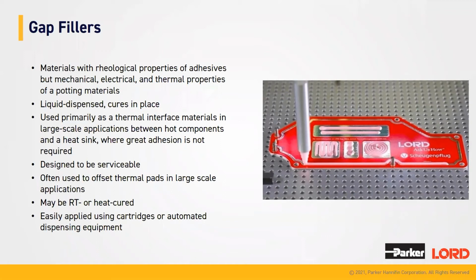Thermal pads require a constant pressure to be applied in application, which means that you're putting a lot more stress on the components, whereas gap fillers, because they're dispensed as a liquid but cure in place, they're able to fill all the small nooks and crannies in each application, but then don't require constant pressure over the lifetime because the liquid nature allows them to flow into everywhere they need to be.